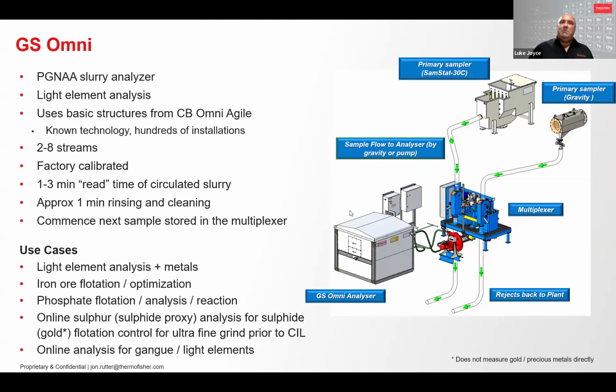So the GS Omni is a multi-stream PGNAA slurry analyzer, able to measure up to 8 streams. It uses the same proven technology as the cross-belt PGNAA analyzers, however, incorporates a multiplexer to sequentially measure sampled streams. Again, the differentiator between traditional online XRF slurry analysis is the ability to measure those lighter elements, and it's not limited by particle size.